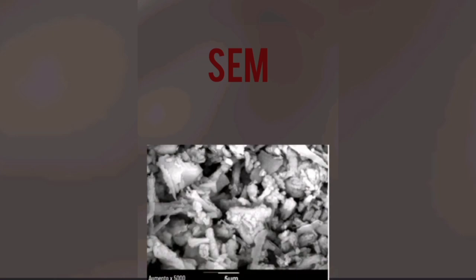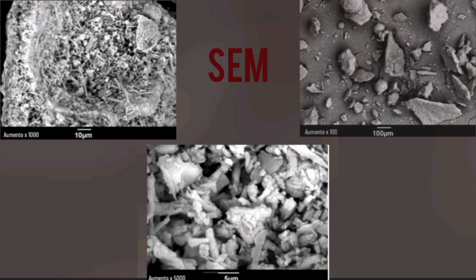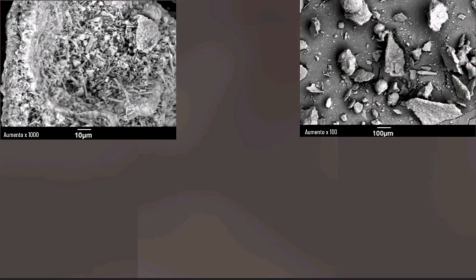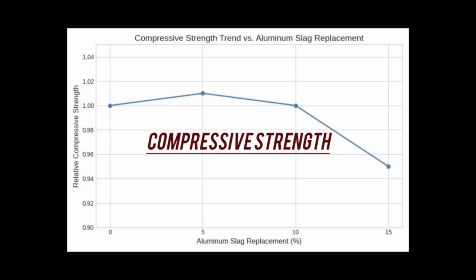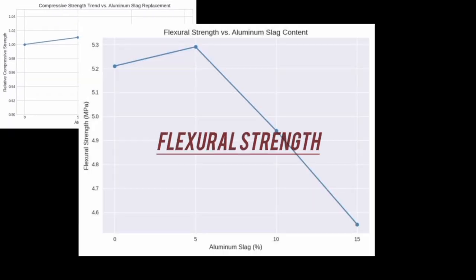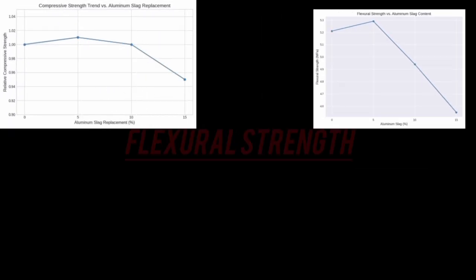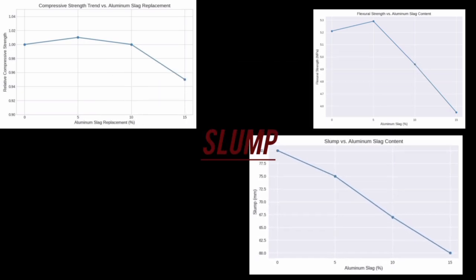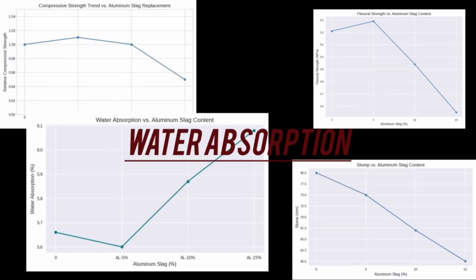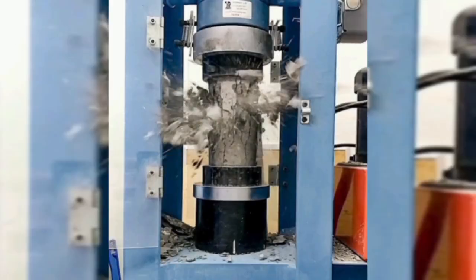For closer observation, SEM imaging is used. These images reveal how particle size and reactivity of dross affect the microstructure of concrete. Finally, test results are analyzed with charts. As the percentage of dross increases, compressive strength decreases to some extent. However, 5% aluminum dross shows the best performance.